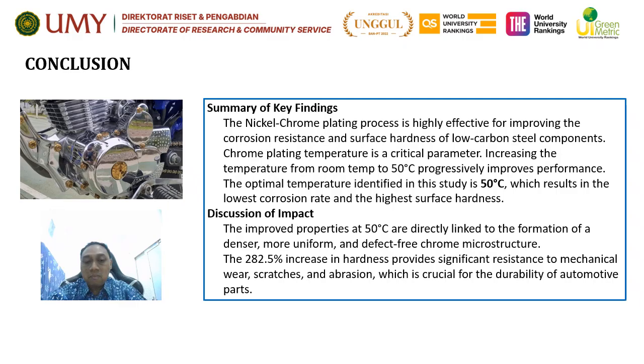The discussion of impact: the improved properties at 50 degrees Celsius are directly linked to the formation of a denser, more uniform and defect-free chrome microstructure. And then the 282% increase in hardness provides significantly improved resistance to mechanical wear, scratches, and abrasion.